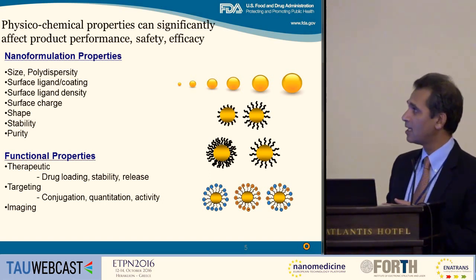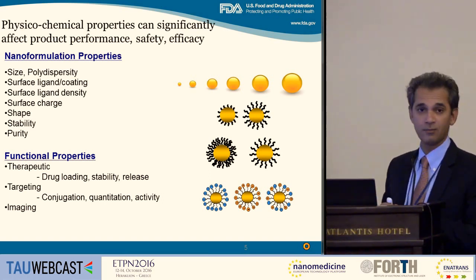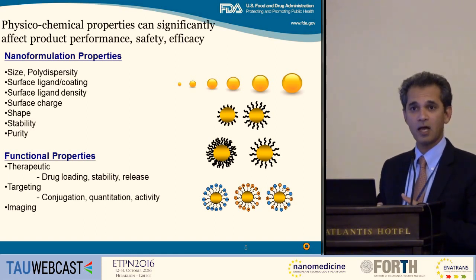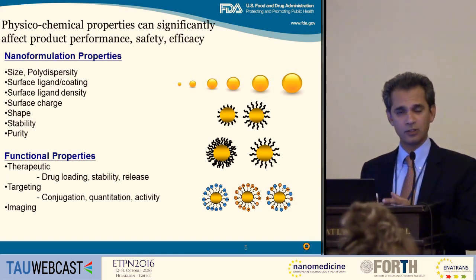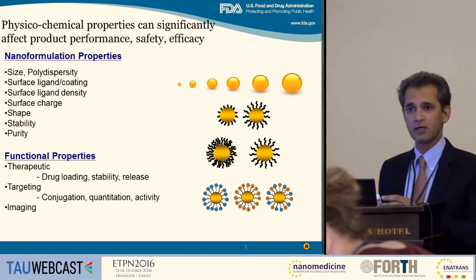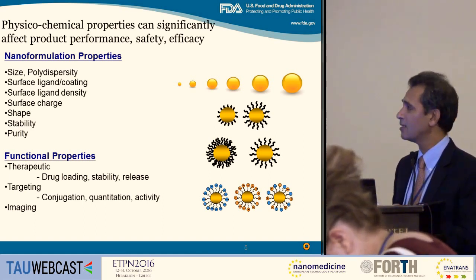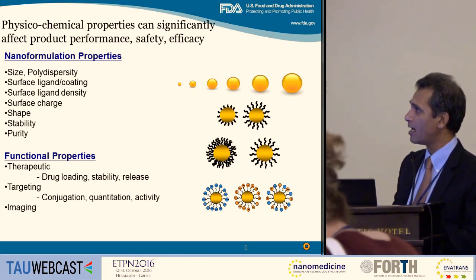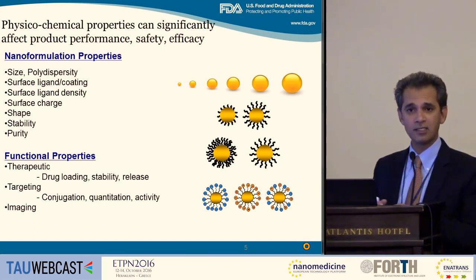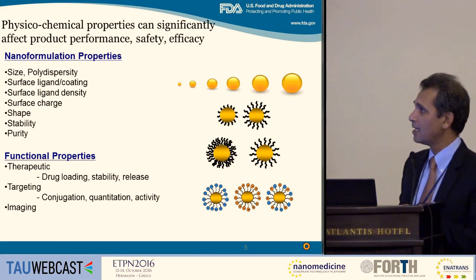The size defines your biodistribution, and the coating also defines those biodistributions. So size and coating are the two most important factors when you develop these. But beyond that, the charge does matter. Cationic particles cause hemolysis. They may have cytotoxicity.